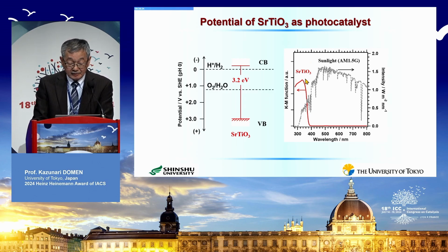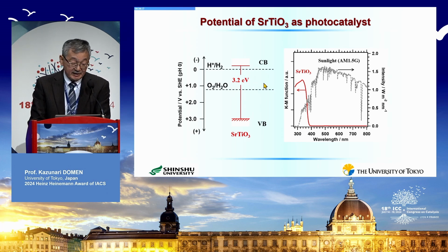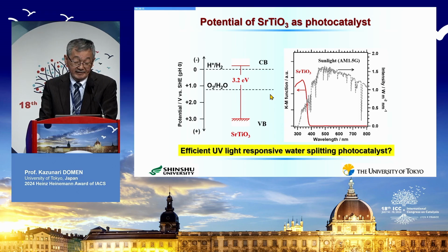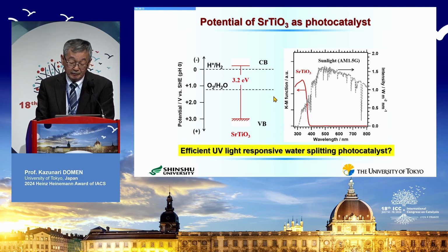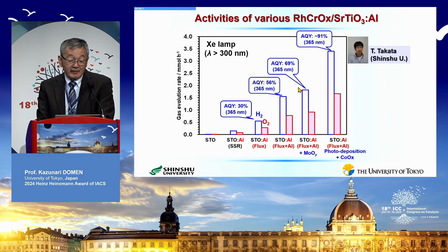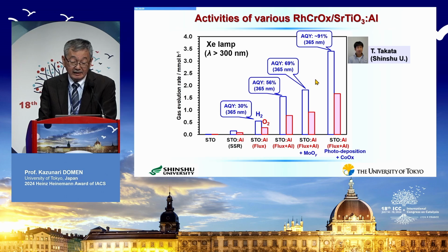This strontium titanate is, as you know, a white colored powder and its absorption edge is located at about 380 nanometers. That means that these materials can use only a small portion of sunlight. However, the band gap position of these materials is suitable to evolve both hydrogen and oxygen. Therefore, these materials have the potential to be efficient UV light responsive water splitting photocatalysts. Here I show the history of development of our strontium titanate-based photocatalyst.